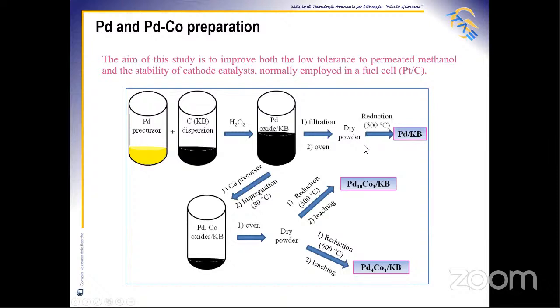A portion of the obtained powder was carbothermally reduced at 500 degrees to form palladium on Ketjenblack, whereas the other portion was ultrasonically dispersed in water and mixed with cobalt nitrate solution. The product was impregnated and dried. So the obtained powder was divided and carbothermally reduced at 500 degrees to obtain palladium 10 cobalt 1, and at 600 degrees centigrade to obtain palladium 4 cobalt 1, after leaching in perchloric acid solution to remove possible traces of cobalt on the surface of the electrocatalyst.